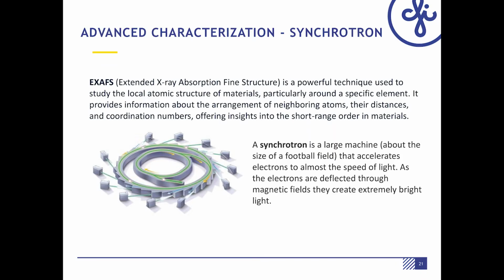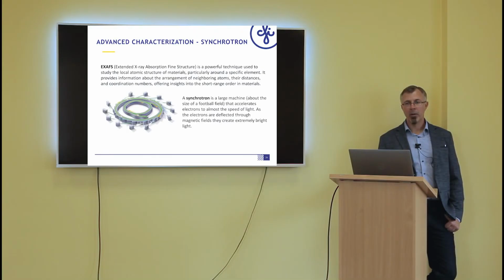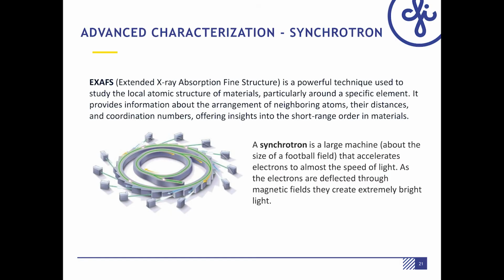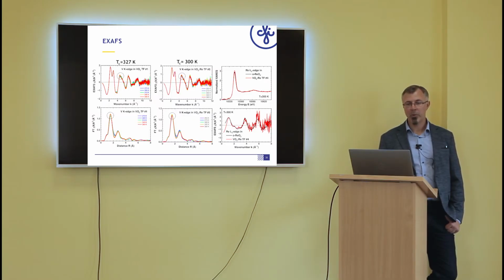For advanced characterization, synchrotron radiation can be used. Synchrotron is a huge machine which accelerates electrons, and if electrons are deflected, they emit quite intense beam of X-rays. One of the methods is EXAFS, or extended X-ray absorption fine structure. These methods allow to probe local atomic surrounding of atoms. As example, I put here rhenium doped vanadium dioxide thin films studied by EXAFS spectroscopy.